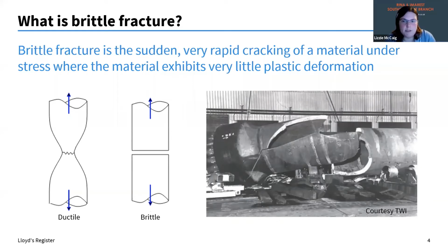The cracks themselves are usually initiated at a stress concentration, such as a pre-existing material defect, or a defect which might develop in service, such as from fatigue. And then the cracks will continue to grow, and they'll increase in magnitude once they're initiated, running perpendicular to the applied stress. Now, in ductile failure, the material starts to deform plastically once yield is reached, and will continue to deform until you hit the UTS. But in brittle failure, there's just no ductile behavior before failure. The fracture is very clean and very sharp, and you don't have much warning that it's going to happen.